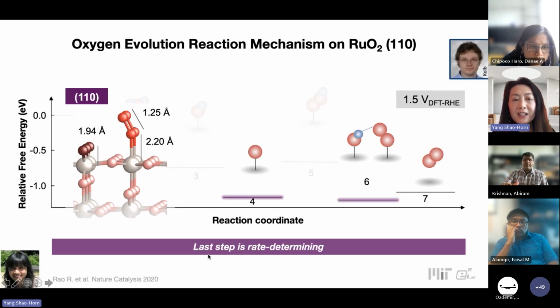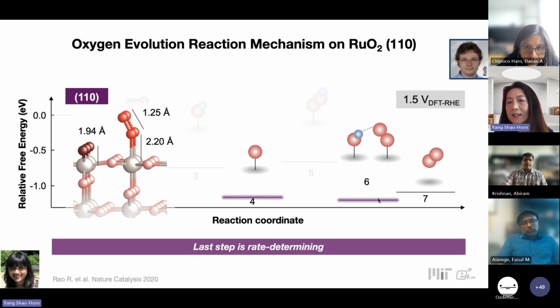We can couple this with DFT calculations to understand the limiting step at 1.5 volts, where the reason we see this superoxide species is due to the binding or stabilization of the proton on the nearby site. If we liberate and deprotonate this hydrogen, then we can evolve and release the oxygen. And this step is rate limiting. So this is one experiment, one example. We can see what the energetic limiting step is and what the active moiety is before the oxygen evolution.